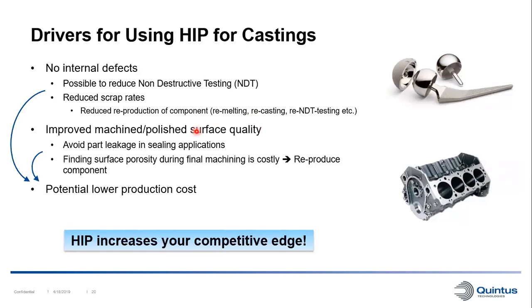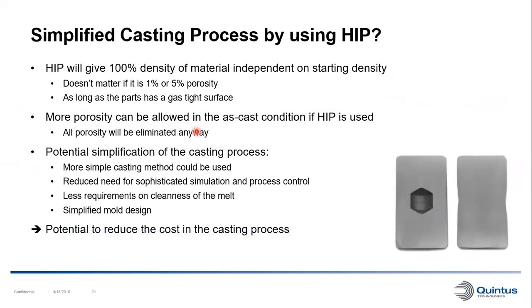So with increased quality and high performance by HIPing and also a potential cost saving, this is how HIP increases the competitive edge. Here I want to talk about an interesting approach that we have successfully tested for additive manufactured material, and that is to allow a higher percent of porosity in the as-cast condition, or in the as-printed condition in that case.